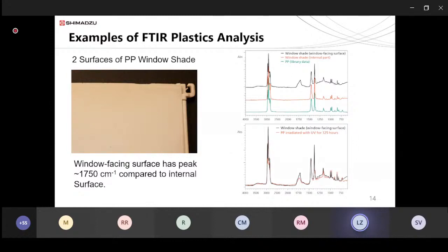So one side of the window shade is facing the window, which means it has more UV exposure. And the other is the internal surface, which has less exposure to the UV radiation. And if we take the spectrum of the two surfaces, we have the black curve as the surface that's window facing, or the outside surface. And the red curve represents the spectrum of the internal surface. And we also have the standard PP spectrum, which is the green curve here. And we can see that the internal surface spectrum is very similar to the standard spectrum. However, the window-facing surface has an extra peak around 1750 reciprocal centimeters. And that peak is attributed to excessive UV radiation.